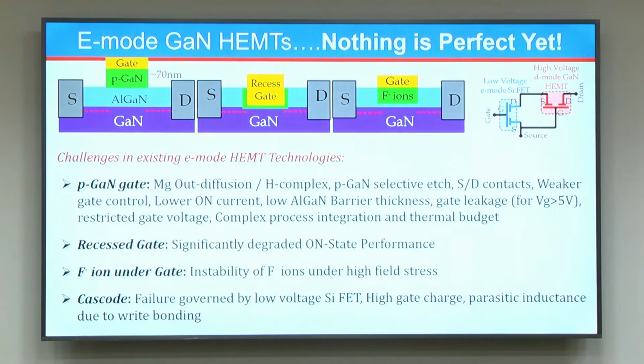So even the stack is realized with a 2DEG concentration which is almost half of what you can practically achieve in a depletion mode AlGaN GaN stack configuration, which leads to lower on current, and you have low AlGaN barrier thickness, so it can also lead to gate leakage. Gate leakage is also introduced further by the pGaN sitting on top of that, which limits the gate voltage to 5 volts. You have also complex process integration and thermal budget.